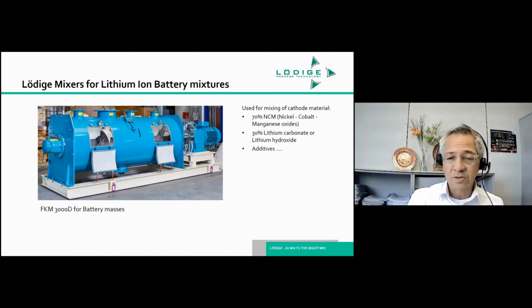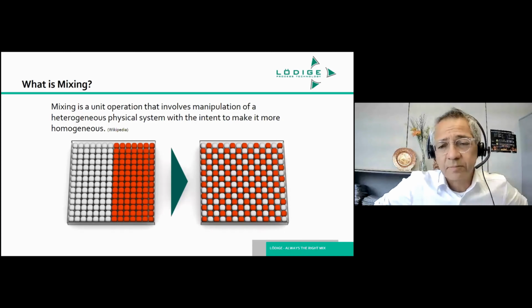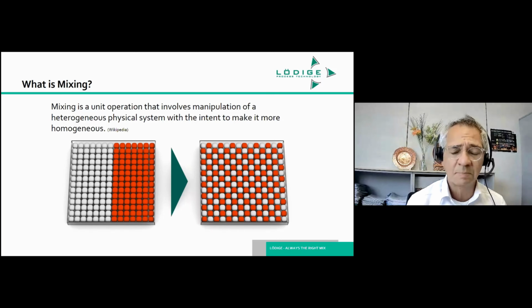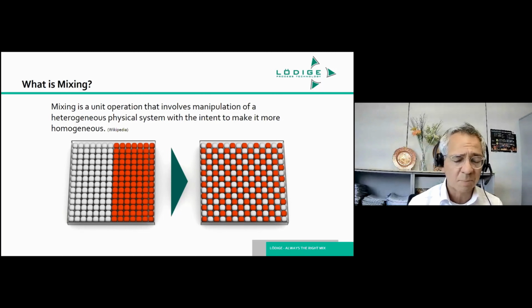Mixing equipment, well, this is what a typical Lödige mixer for battery masses can look like. In this example here, it's a 3,000 liter mixer in total volume. It's used for mixing the NCM, the nickel, cobalt, manganese oxides, together with lithium carbonates or hydroxides, and additives in powder form as are necessary. Why mixing? Well, the masses that are to be put together are of different physical properties. Some are lumpy, there are different proportions, and so on. So you need to mix in advance to get to the actual mixture that is required for your cell production.